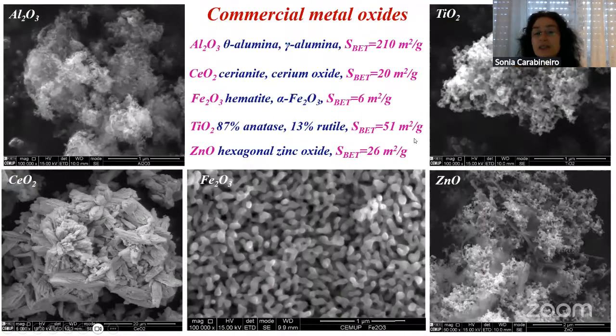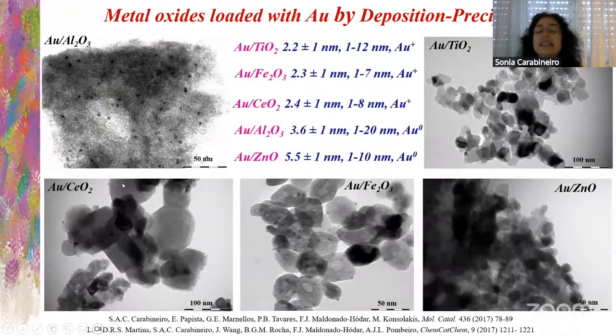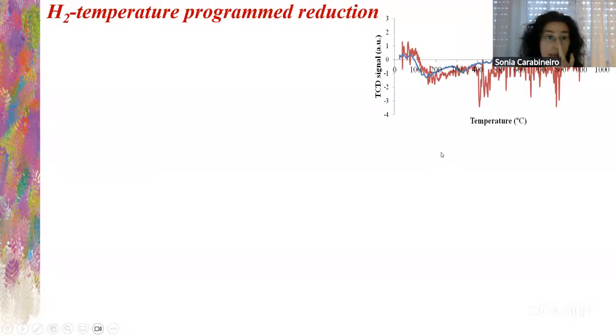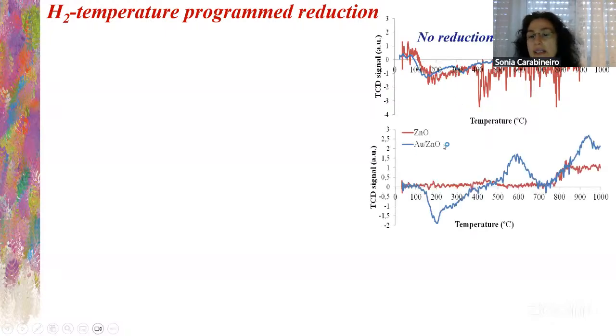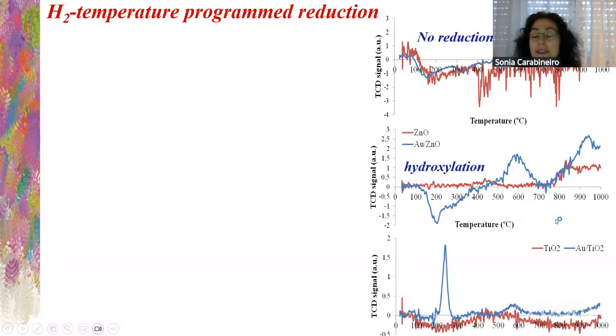Here we have several commercial oxides, and gold was added to these oxides by deposition precipitation. If we do a temperature programmed reduction, with aluminum oxide there is almost no reduction. With zinc oxide, there is a small peak, that's hydroxylation of the zinc. The peak with titanium dioxide is for reduction of gold, because titanium oxide also has no reduction peaks.